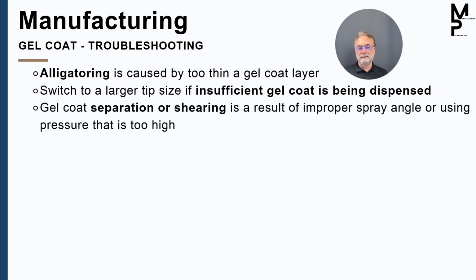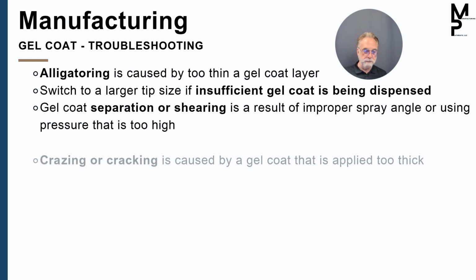It's that simple. Now, if I'm spraying and I'm not perpendicular to the part, I'm spraying on a sharp angle, I can actually separate the gel coat from the fillers and the pigments. So proper spray angle is important in two ways. One, it can shear the resin out of it. But also, if I'm not perpendicular, the part closest to me is thicker and the part furthest away from me is thinner, and I'm getting an uneven coating distribution. As we get into the resin curing technology, you're going to see that thicker resin cures faster than thinner. So if I have thick areas and thin areas, the thick areas are going to cure faster than the thin areas. As they cure, they're going to start shrinking, and I could get a pre-release problem in the gel coat by having just simple uneven gel coat.